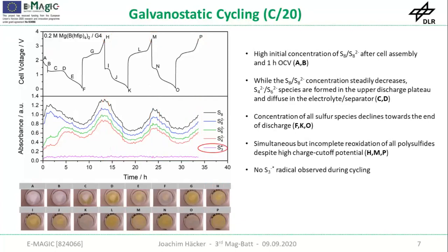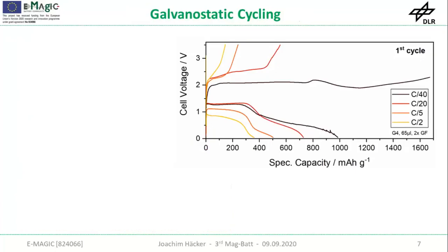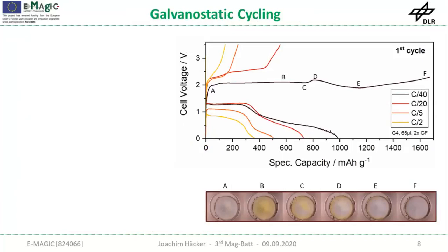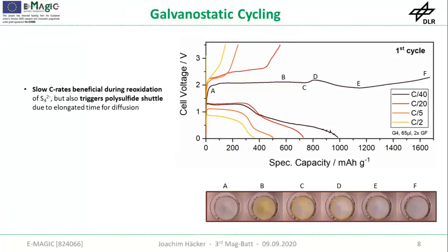In fact, no S3 radical was observed. This is in agreement with the former studies by Häcker done 2 years ago, something like that. One can argue that with the lower C rate, it's possible to achieve this complete reoxidation, which is in fact true. So you can see here that at the end of the charge at point F, the separator is decolored again. But this also triggers the polysulfide shuttle.